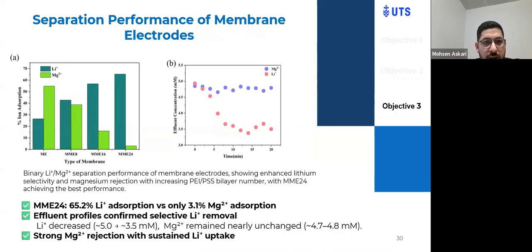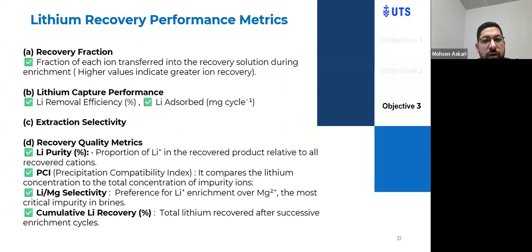In the first stage, a binary lithium-magnesium solution, each at 5 millimolar, was tested, and the number of LBL layers was optimized. The result shows that 24 layers of positive and negative layers give the highest efficiency. Also, the effluent concentration shows lithium decreased from 5 to 3.5 millimolar, while magnesium remained nearly unchanged. That shows magnesium did not penetrate this layer.